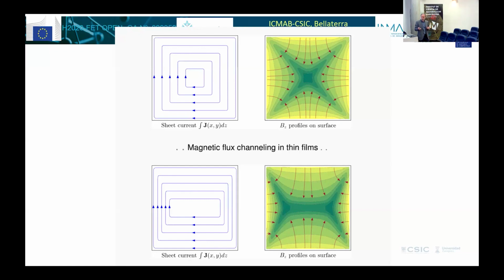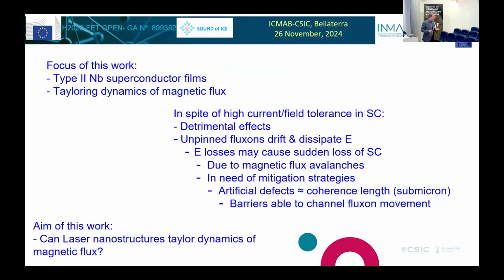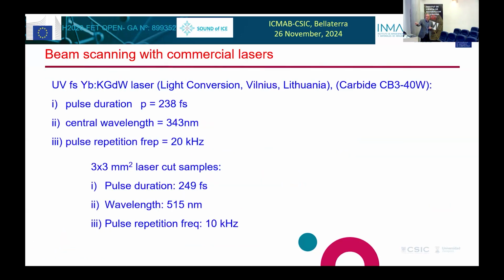These are films. So there are films over silicon, for example. They're very thin films. So we need to use the femtosecond laser, not only because we make these nice nanostructures, but also because to treat a very thin film, you need a very short pulse laser so that you don't destroy it, and you can work with it and modify it. And so I'm not going to spend too much time on this, but basically we use a 238 femtosecond pulse laser with an emission of 343. We use 20 kilohertz or 10 kilohertz repetition rates in order to avoid accumulation of heat, because each femtosecond pulse does not input heat,